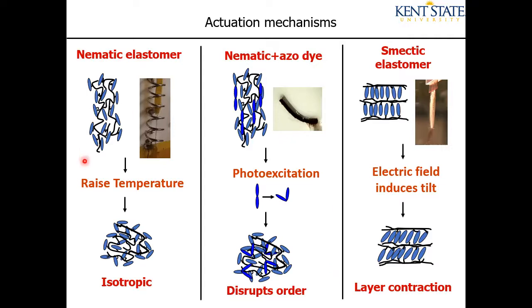Why would the material respond to heat? Well, here we have a polymer. This cartoon shows a polymer backbone with the liquid crystal dangling off of it. When it's cold, those molecules are aligned in a nematic phase, and when it's hot, they go into an isotropic phase. When they disorder their orientations, they drag the polymer chains with them, and they make the material shrink along the axis of nematic order. So that's an order-disorder driven strain.